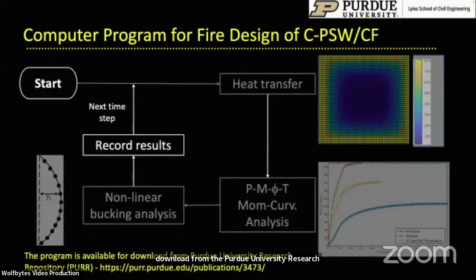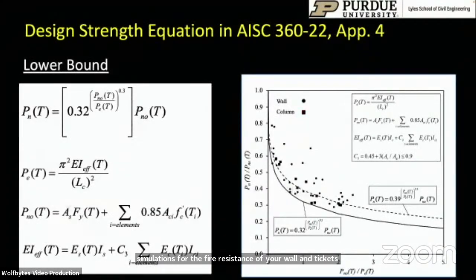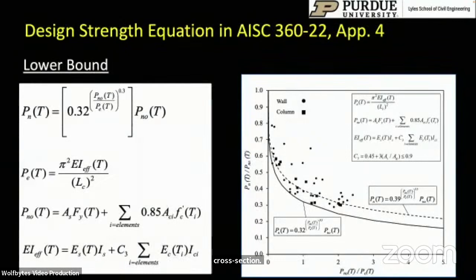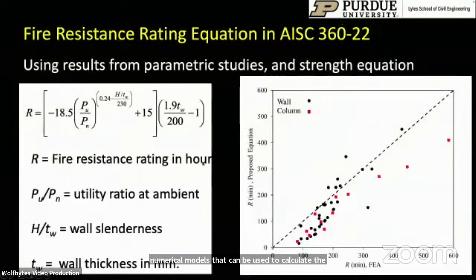You can download the program and you can run various simulations for the fire resistance of your wall and check its design. And we used all of these results in order to develop the fire design equations. For example, we developed equations for calculating the compression strength as a function of temperature. Pno is the compressive strength of the cross section. Pe is the buckling strength of the wall. And together it gives me the axial capacity of the wall as a function of temperature. I can calculate the temperature from the fire and I can estimate the axial load capacity. So there are equations that are based on test data and numerical models that can be used to calculate the strength of the wall. Or if you are just looking for the fire resistance rating equation, we've developed that as well as a function of the applied loading, the H/tw, which is an important parameter, and the thickness of the wall.